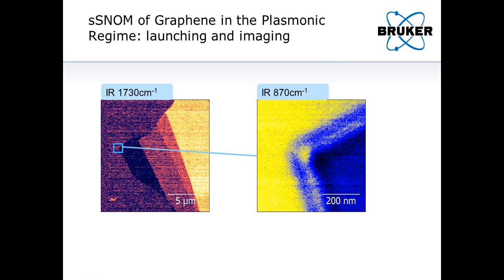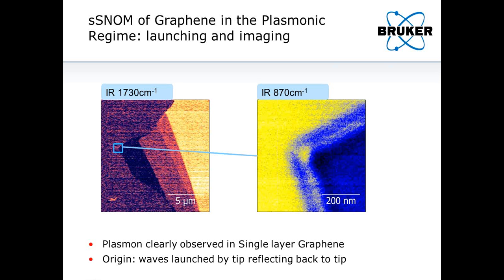Here I'm showing the graphene plasmon image at 870 wave numbers. The origin of the waves shown in this image is due to the plasmonic waves being launched by the tip and reflecting back to the tip.